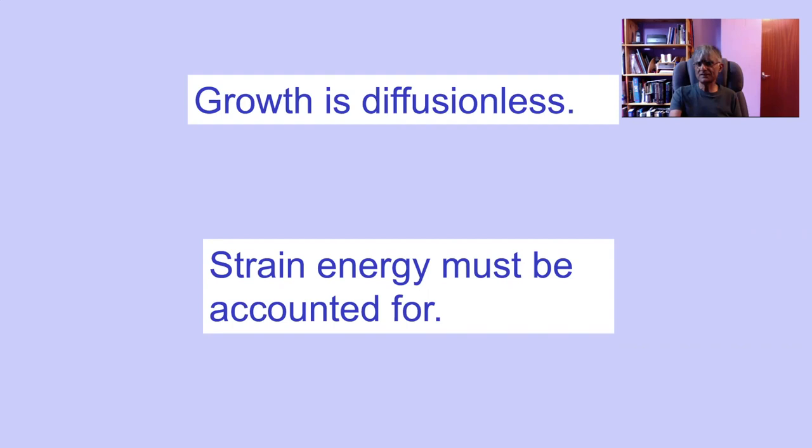Now there are many other consequences of this simple set of conclusions. One is that if we can observe individual platelets of bainite growing, then they would grow much faster than permitted by the diffusion of carbon. Okay? And note my emphasis on individual platelets, which are of the order of a quarter of a micrometer in thickness. So things like hot stage optical microscopy or confocal laser microscopy are no good.